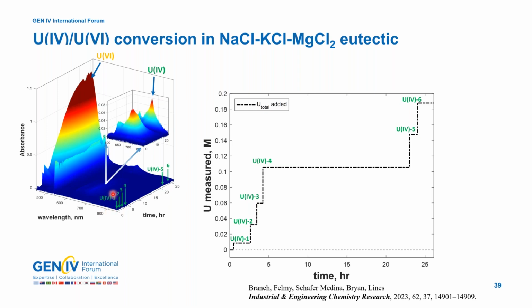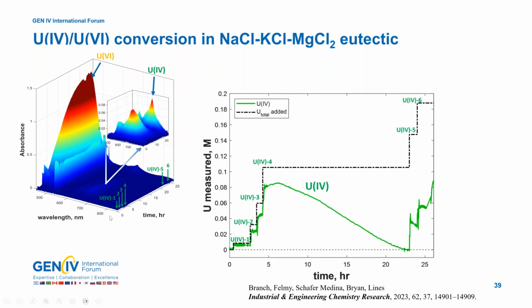So we start with clean salt. We have 4 additions of uranium-4. We see immediately the uranium-4 signature in the mid UV vis range. And then also we see the conversion over to the uranium-6 band over in this region here in the spectrum. And immediately when we add uranium-4, we get the signature of uranium-4. We can measure the concentration with our chemometric model, and we see the uranium-4 increase. But we also see the uranium-4 decrease over the course of time and under the conditions of this experiment.